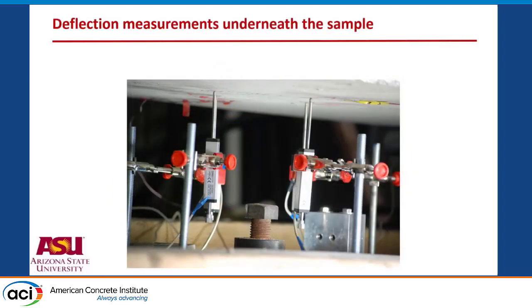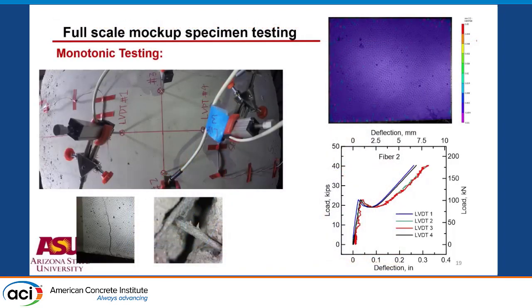I will show. So these are the LVDTs. A significant number of LVDTs to measure the response, underneath the sample. Now let's see if it runs. Here you're looking at underneath the sample, as if you crawled under the sample, and the load is being applied to it to cause the static failure that we have. You would see a horizontal crack forming an opening as the load is applied in the middle.